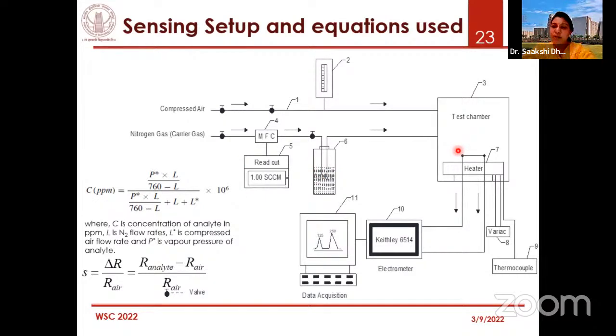Now, if I talk about alcohol sensing in breath, this is something that we need around 300 ppm, right? So there is really no requirement to go to something like ppt or really low levels of ppb, right? So by controlling these three conditions, we could get sub-ppm to even higher levels, say 700 ppm of the concentration of alcohol and other VOCs.